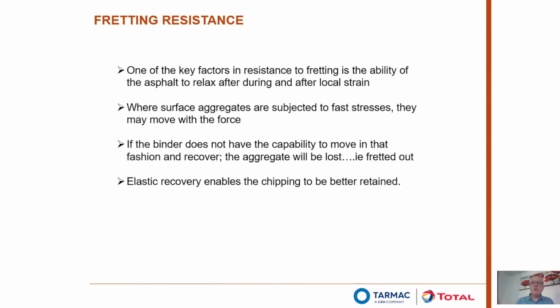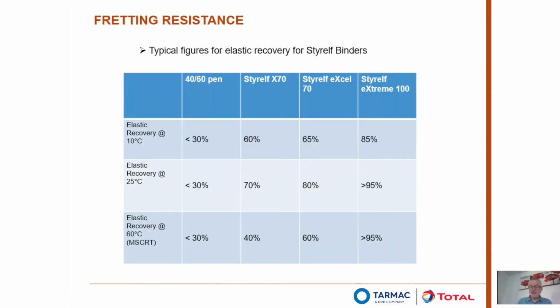And that's because one of the key factors in resisting fretting is the ability of the asphalt to relax after strain. Okay, so as I mentioned before, it's very often where you get fast stresses impacting on the surface aggregates that you lose them. That's what fretting's all about. But if the binder doesn't have the capability to move with the aggregate and recover, then the aggregate will be lost. So elastic recovery is critically important in this area.